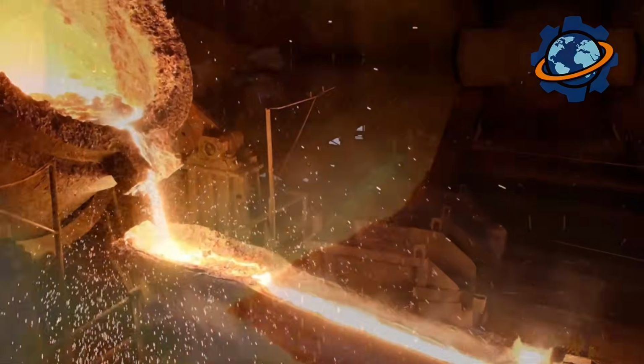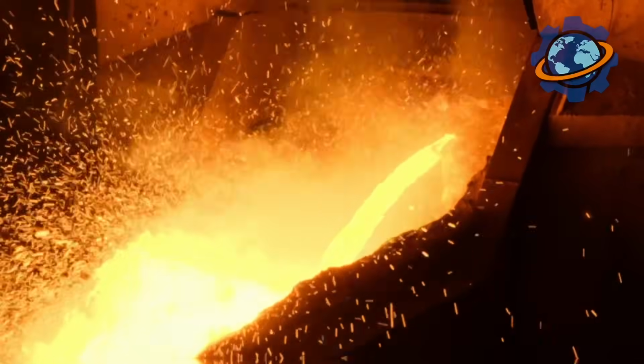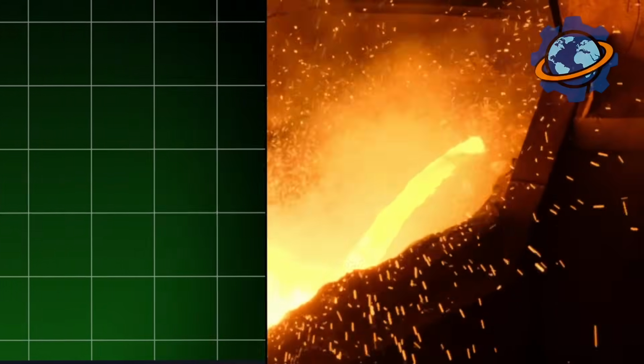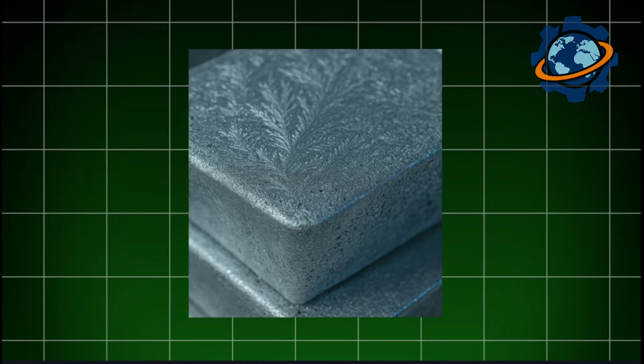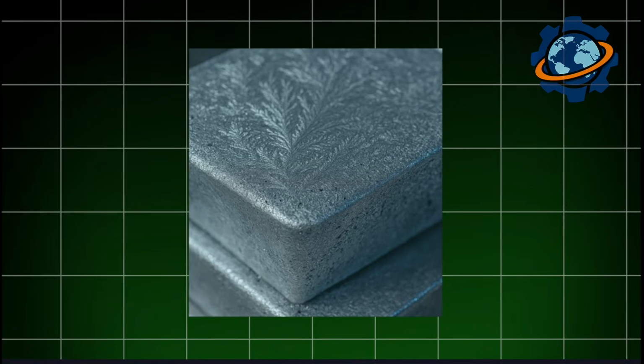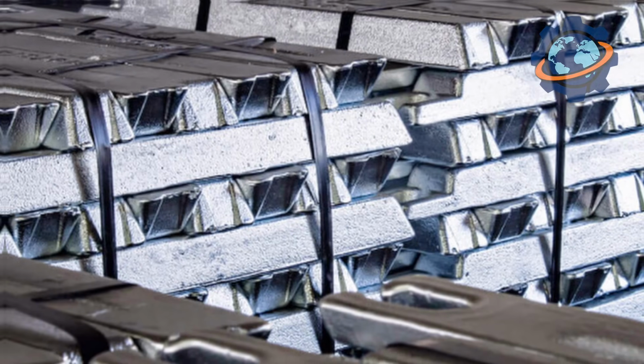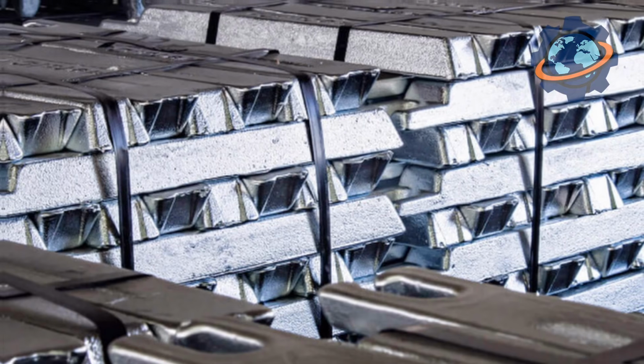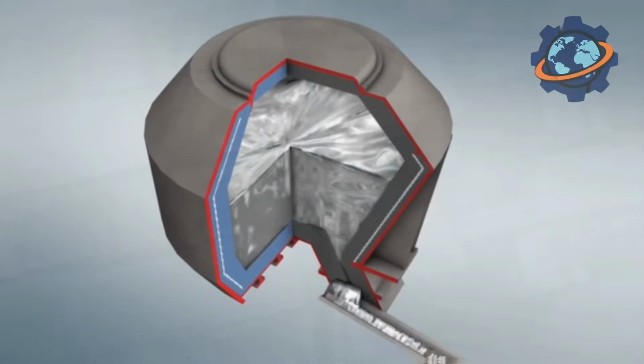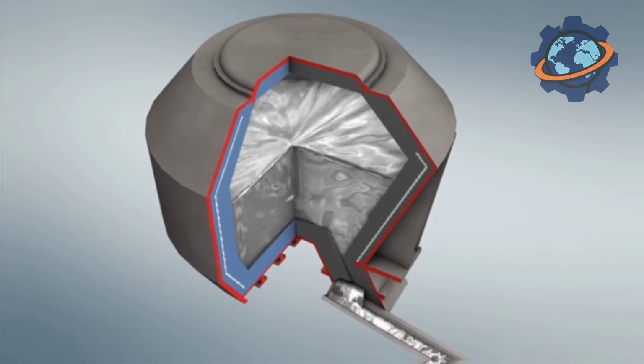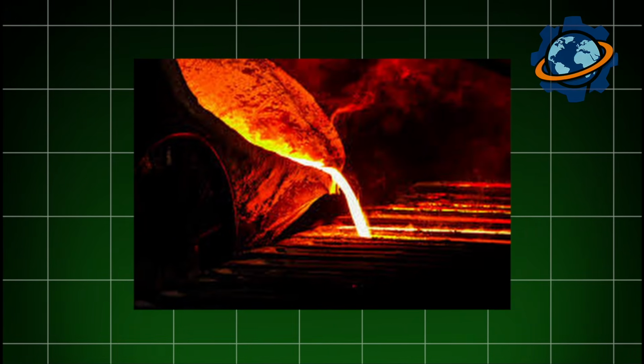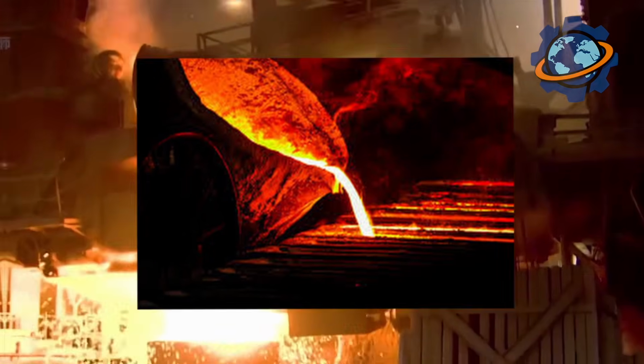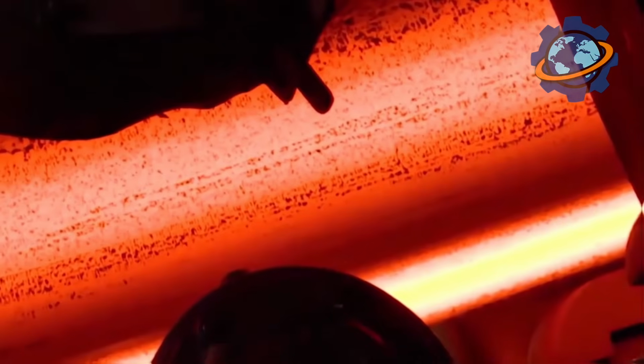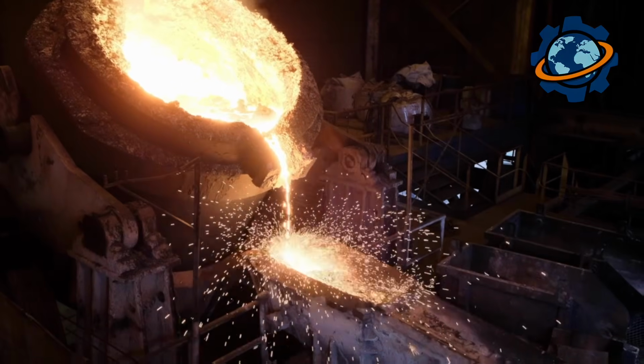On the ingot surfaces, a characteristic pattern forms, crystalline designs resembling frost flowers on glass. This is called zinc flowers. Ingots are stacked. Zinc is ready for use. But its main application awaits in hot-dip galvanizing baths. There, steel products will receive corrosion protection. The process looks impressive, like baptism of metal by fire. A steel beam 40 feet long is immersed in a bath of molten zinc. Temperature 840 degrees. The beam completely disappears in the silvery liquid.